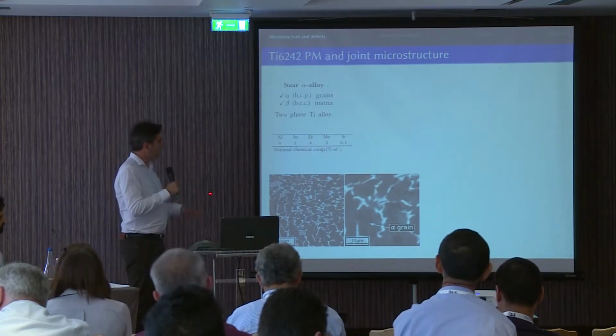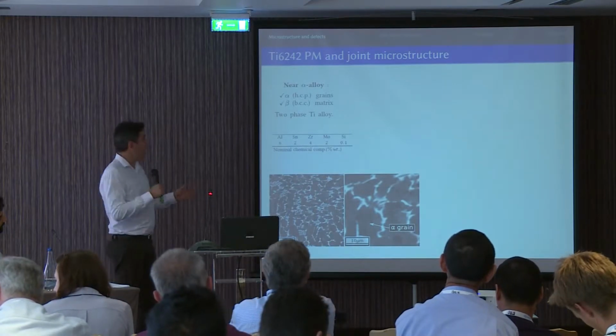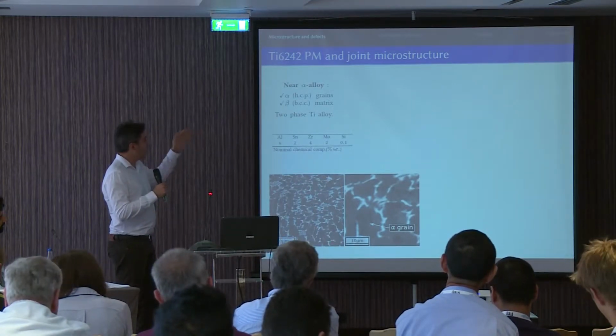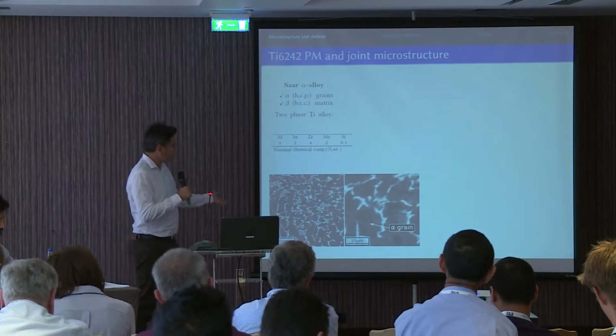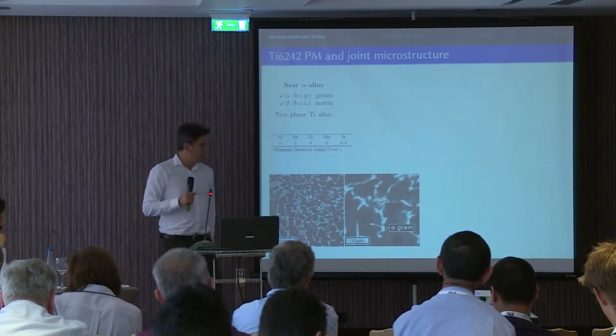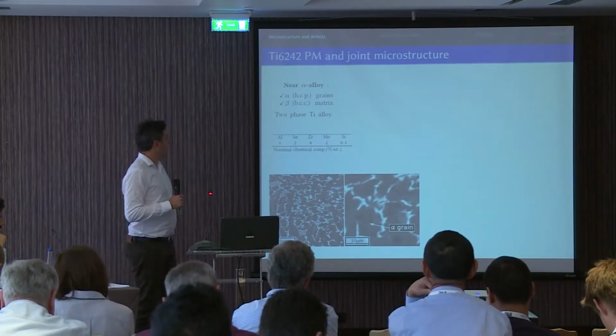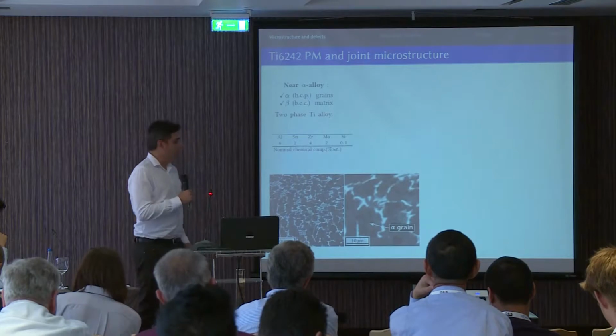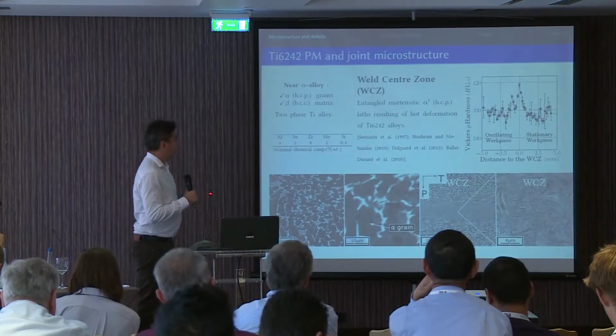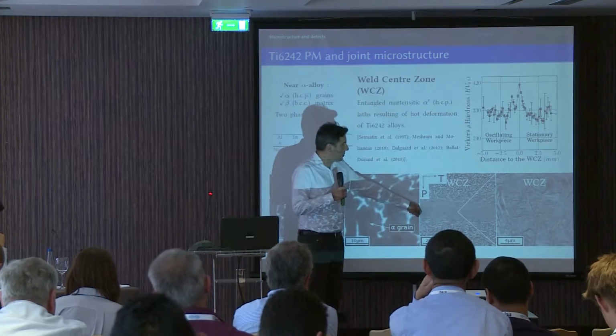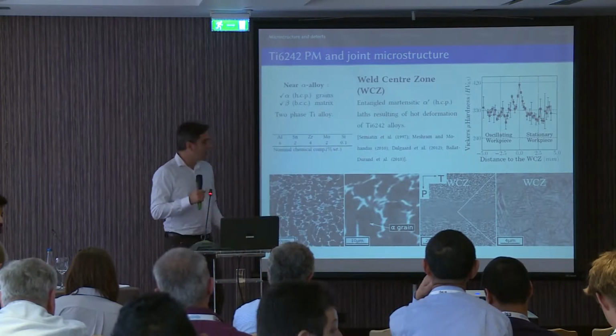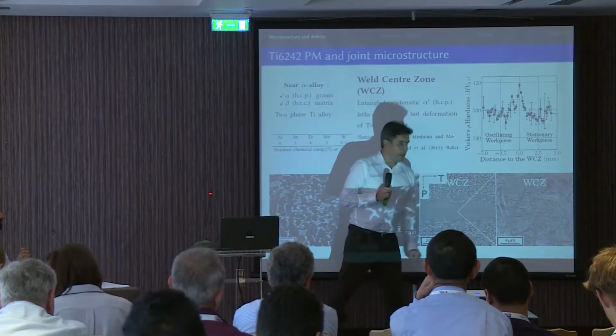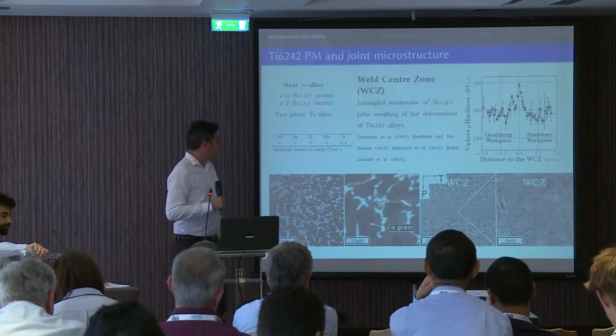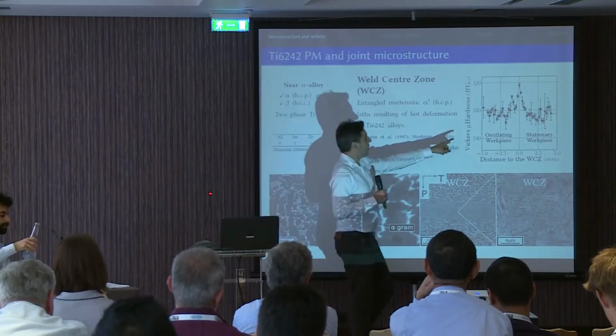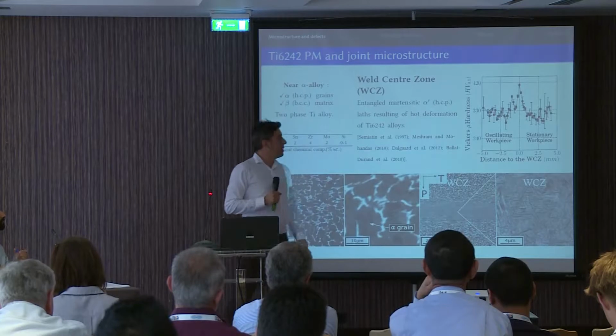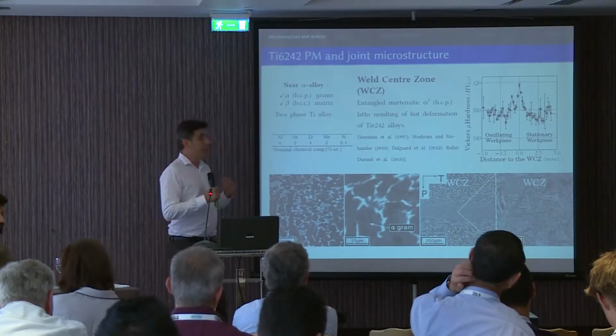We have chosen a two-phase titanium alloy with alpha grains situated in the beta matrix. Here's the microstructure: you have grains of 10 or 20 microns. The first question: what is the effect of the weld? As you can see here, we have produced what we call the weld center zone. We have a very fine alpha prime entangled acicular microstructure, which shows an increased micro hardness. This increased micro hardness suggests a higher tensile strength.